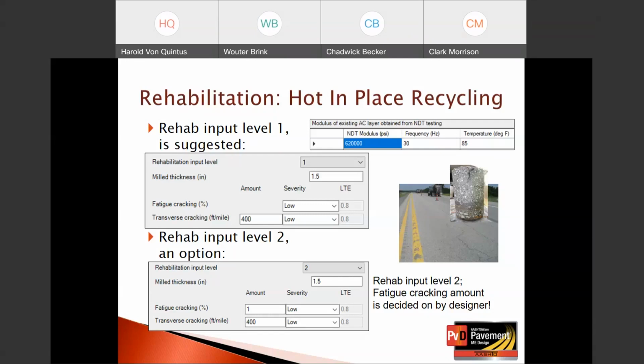For rehab input level 1, I'll come back to this. As shown in the drop-down box on the right in blue, the back calculated average elastic layer moduli for the existing asphalt layer is 620,000 PSI at a frequency of 30 Hertz and at an average mid-depth temperature of 85 degrees Fahrenheit. A rehab input level 2 can be an option. If there's minimal cracking at the surface and we do not have FWD testing available, what is our amount that we're going to enter? And so for rehab level 2, I entered 1%, and I did that for a specific reason that I'll show in just a minute, low severity.